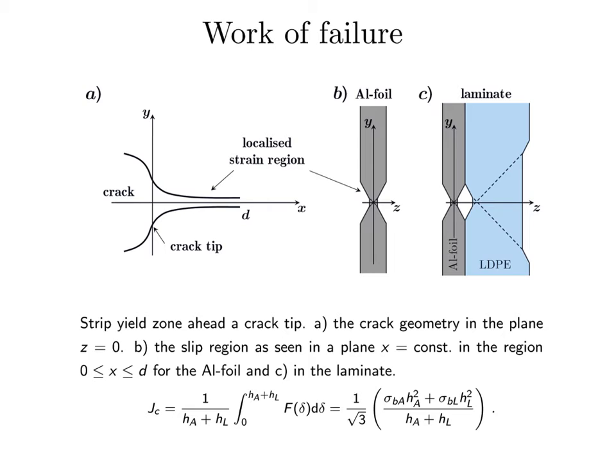Here you see to the left the crack, with exaggerated displacements and opening of the crack. The crack tip is at the origin of the X and Y coordinate system, and you can see the crack opening displacements. What you have ahead is the character of the necking, which has a maximum opening at the crack tip and then gets thinner and thinner. And to the right you see the necking type of failure of both the freestanding aluminium foil and the laminate.